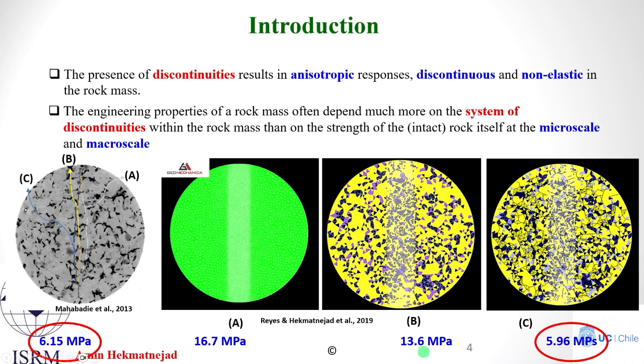In the third experiment, based on thin section and microscopic analysis, the stochastic parameters of the system of microfractures were introduced into numerical modeling. The results are quite close to those observed in the laboratory. As you can see, the obtained results based on the numerical modeling here, incorporating both mineral heterogeneity and microcracks into numerical modeling, is 5.96 megapascal, which is quite close to the experimental result of 6.15 megapascal.